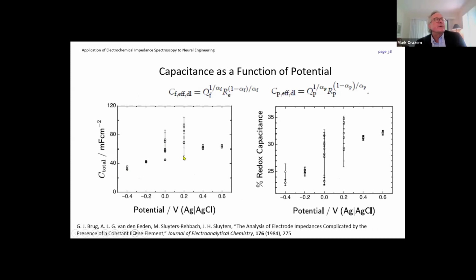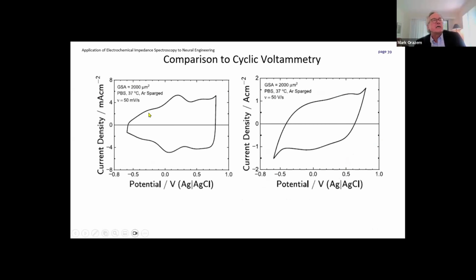So if we look at the total capacitance as a function of potential, what we're seeing is that the capacitance is on the order of between 40 to, say, 100 millifarads per centimeter squared, and it varies with potential. And the percentage of that that's due to the iridium oxidation and reduction ranges from about 25% to about 35%.